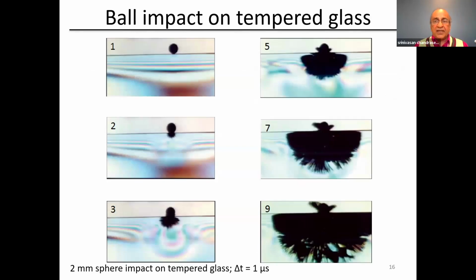Now, this is another high-speed sequence. This is not taken from a Rupert's drop. It's taken from the impact of a little tungsten carbide sphere, 2 millimeters in diameter, hitting the surface of toughened, bulletproof glass at 150 meters per second. This is taken in polarized light. Polarized light shows up the stresses.